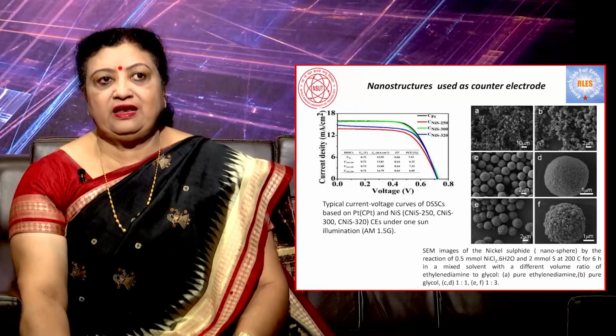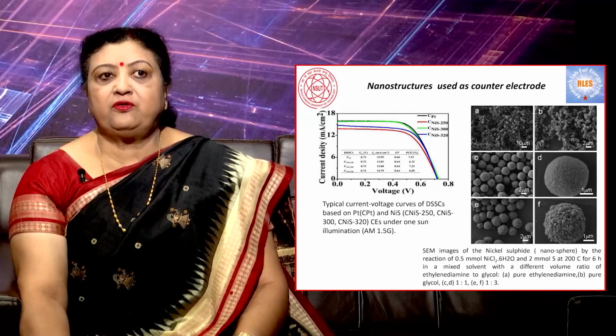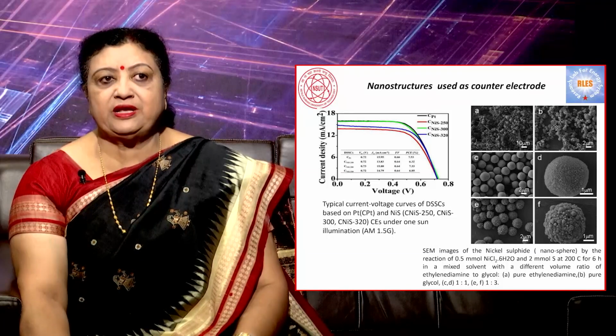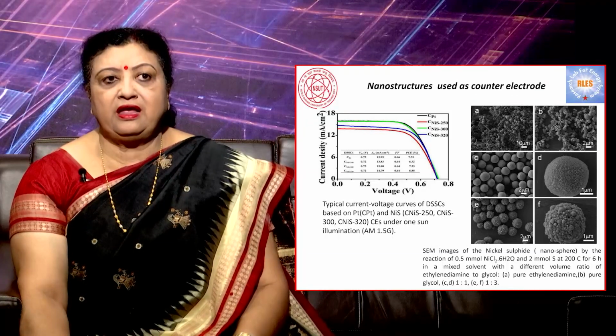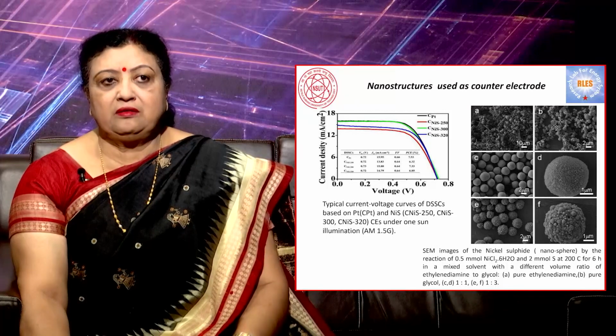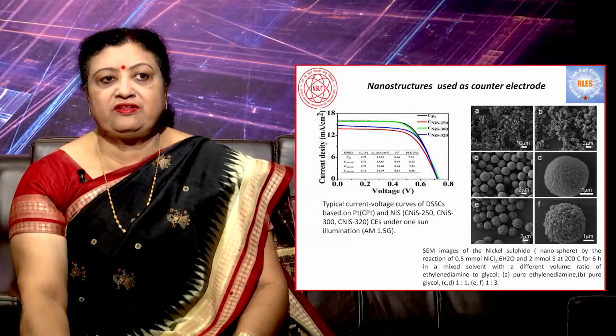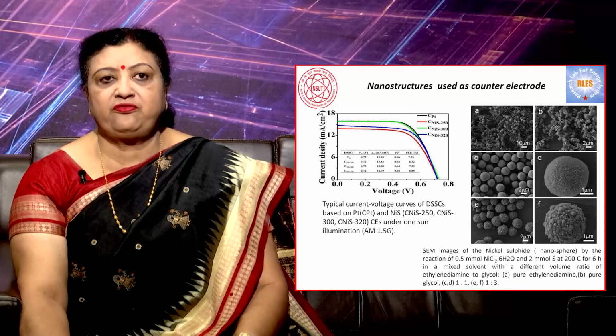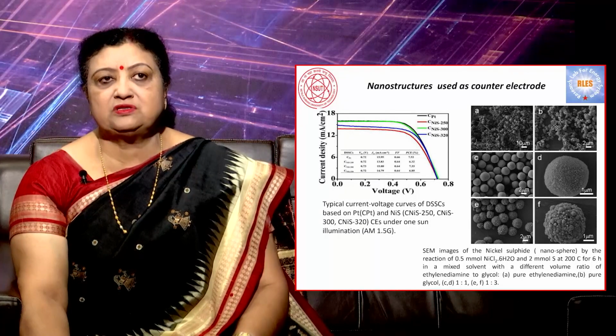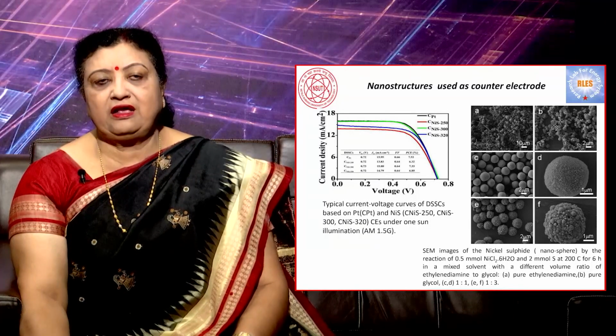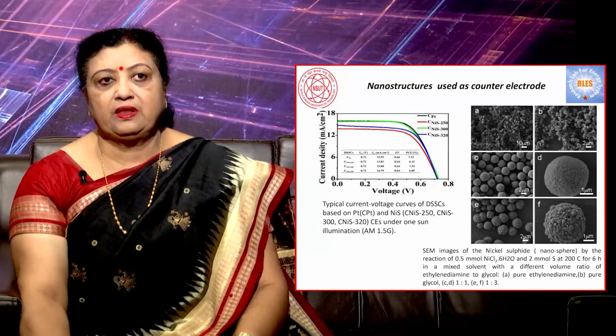Nanostructures used as an electrode. The typical current voltage curves of the DSSC based upon platinum and NiS under one sun illumination, that is AM 1.5 G, and the different nanostructures of different dimensions have been shown here, which can be used, and these nanostructures of NiS can be used as a counter electrode.